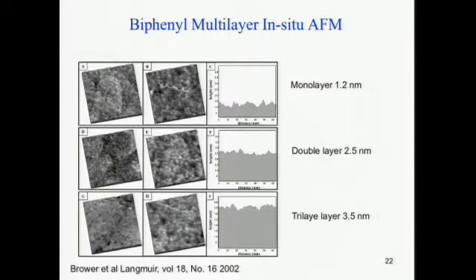Other techniques that were used: we want to look at the roughness of the surface. At this time, people weren't really that good at getting aromatic systems to form the same kind of ordered layers as they did with the aliphatic systems, the alkane thiols I was telling you about. So looking at the roughness was about as good as you could get to understanding that. Here you can see this right here is actually a gold terrace, and this is a monolayer. If you go across this monolayer, you can see the roughness, and we also measure the thickness. As you continue to make multiple layers, you see that the roughness does increase a little bit, but the thickness is still on par with the number of layers that you expect.